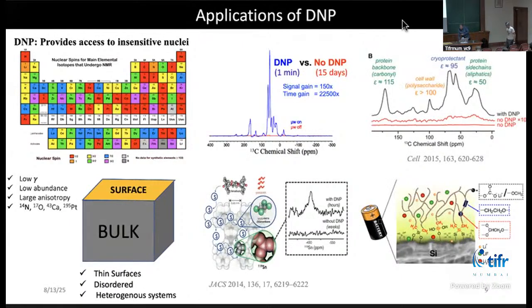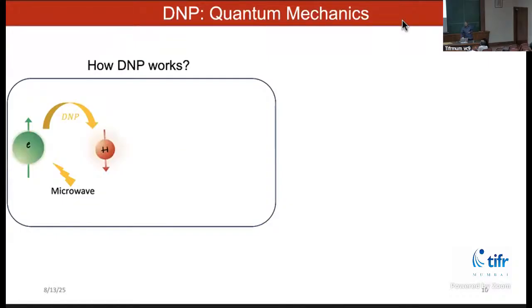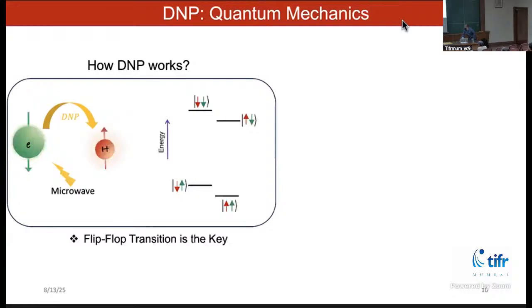Before I go to that slide, I'll tell fundamentally, since there was a question, how does DNP work? So fundamentally, it works through a spin flip-flop process. So there is an electron spin, and this is polarized along the z direction of the magnetic field, and then there's a nuclear spin against the magnetic field. When we shine microwaves, we want to shine them at a specific resonance condition. So this is a two-particle, 4 energy level diagram. And what we want to do is induce the flip-flop process. So imagine the green is up, red is down. We want to induce a transition such that it causes a flip-flop of electron and proton.